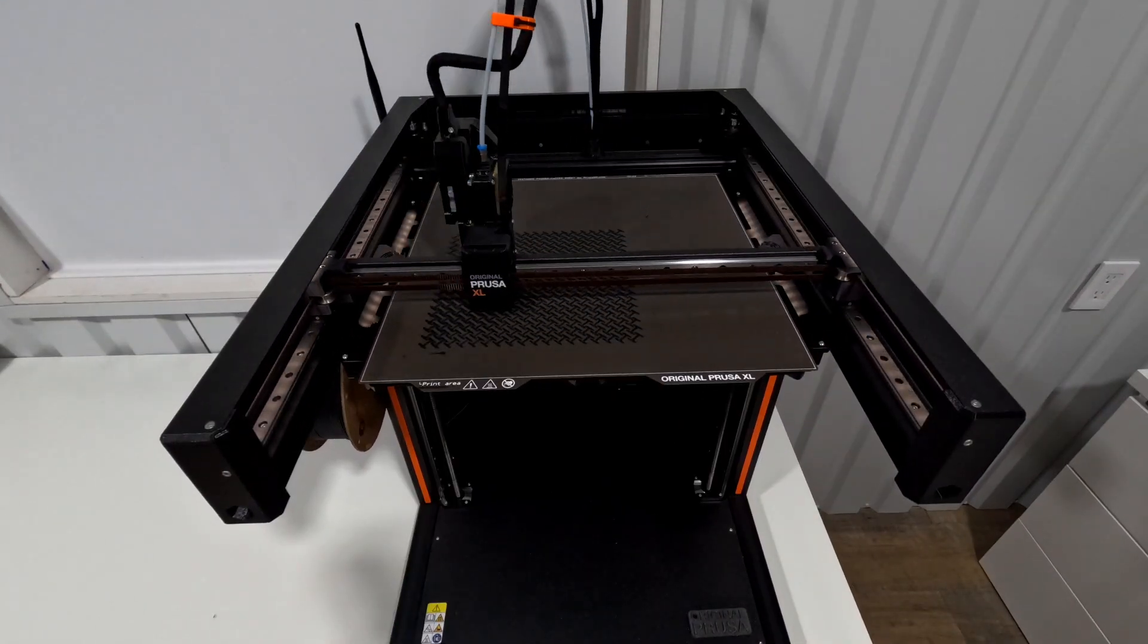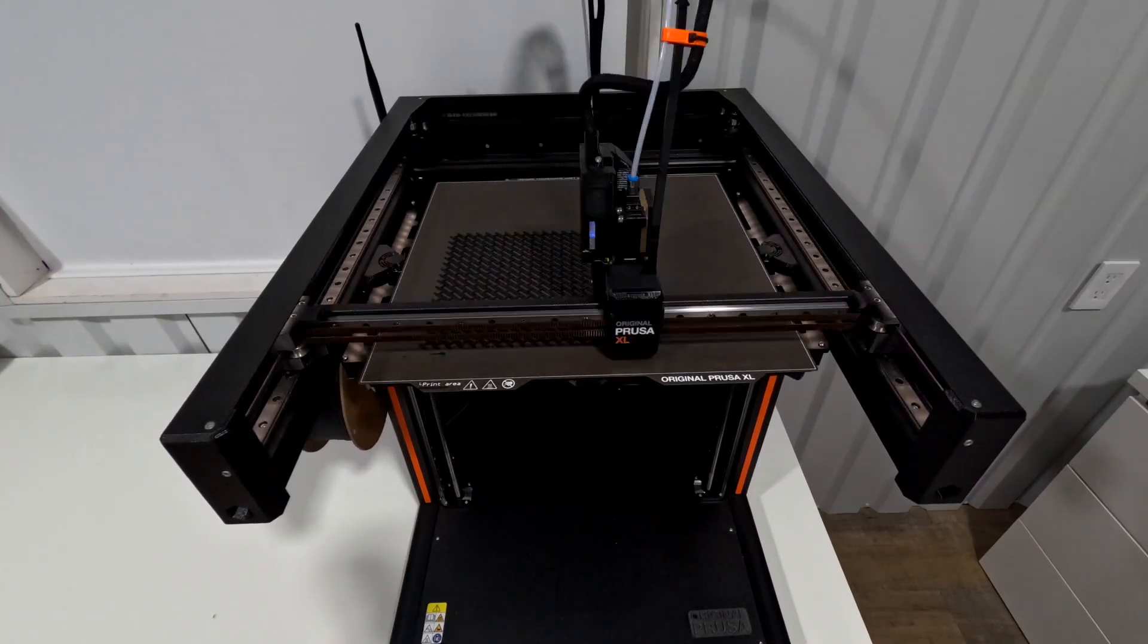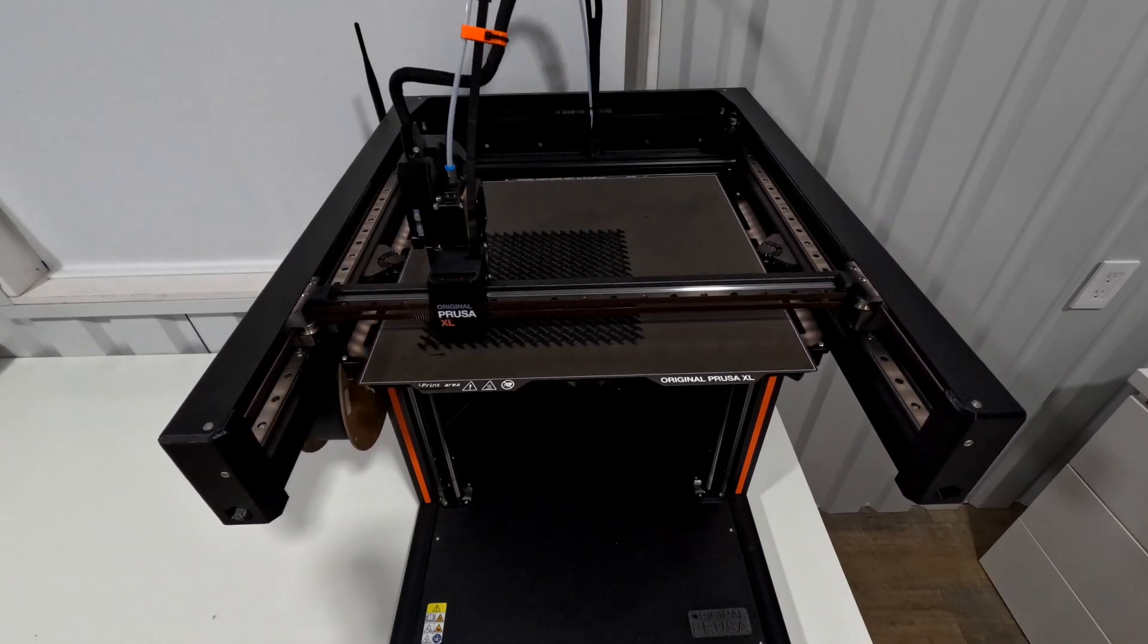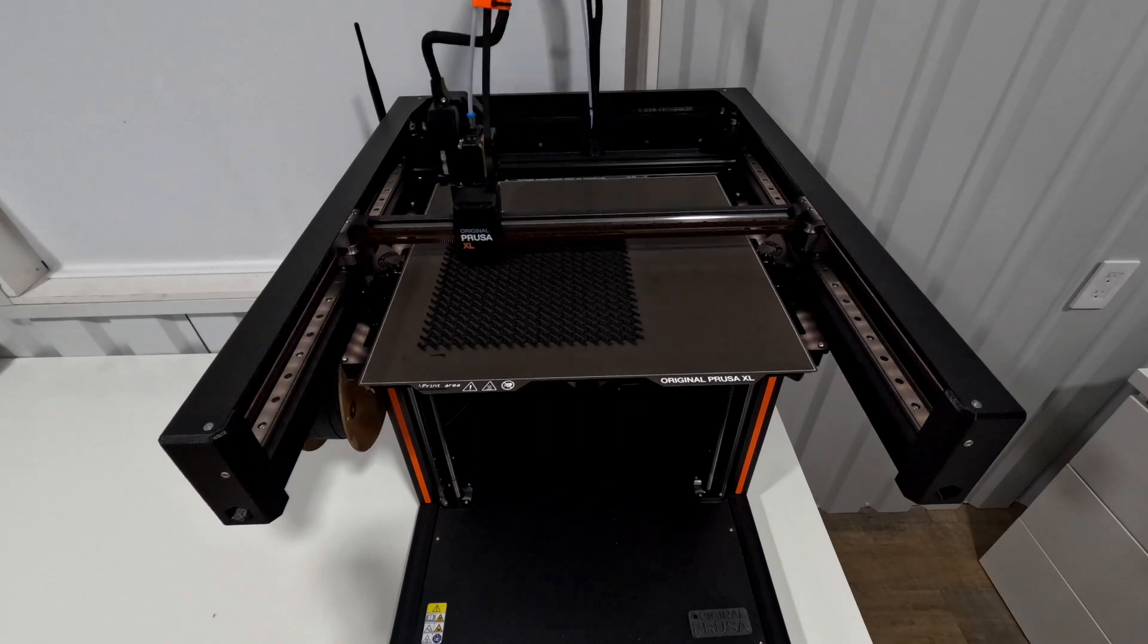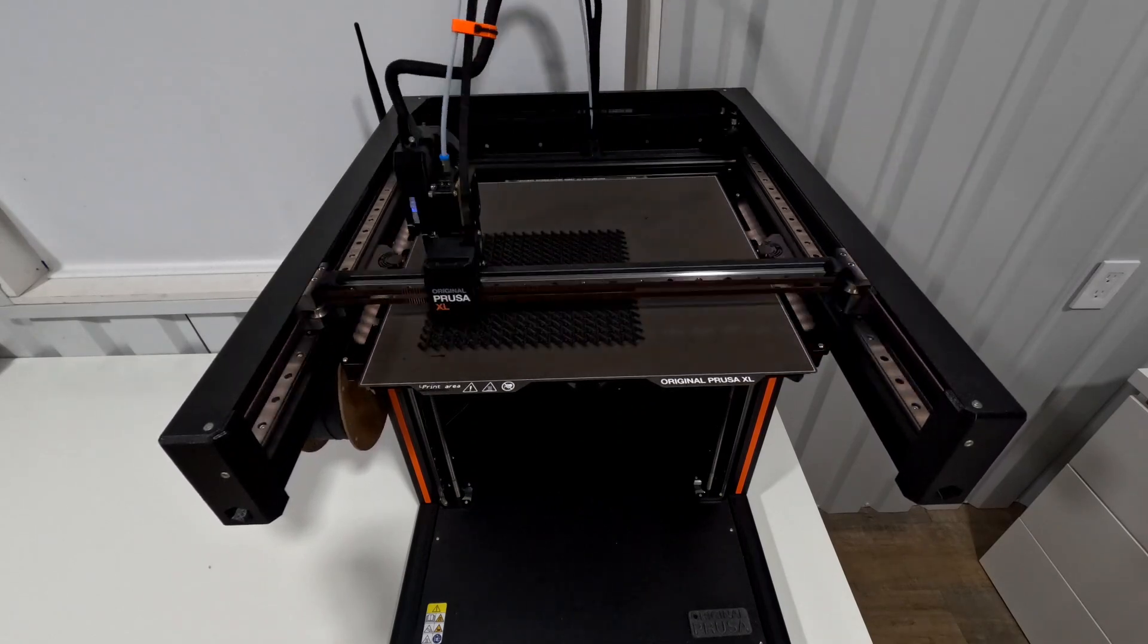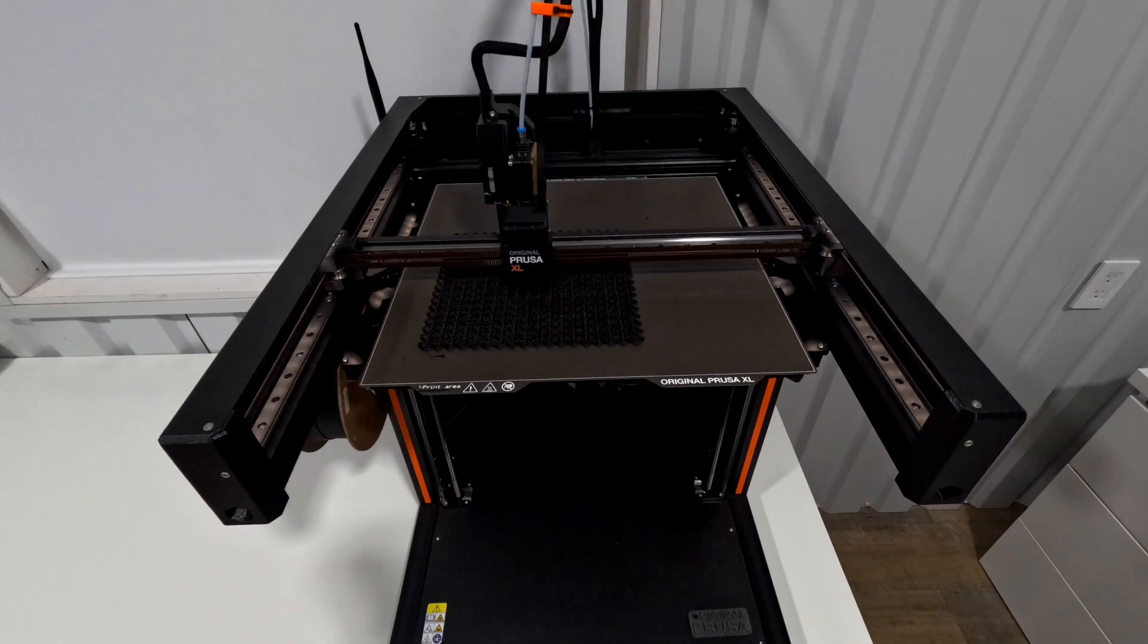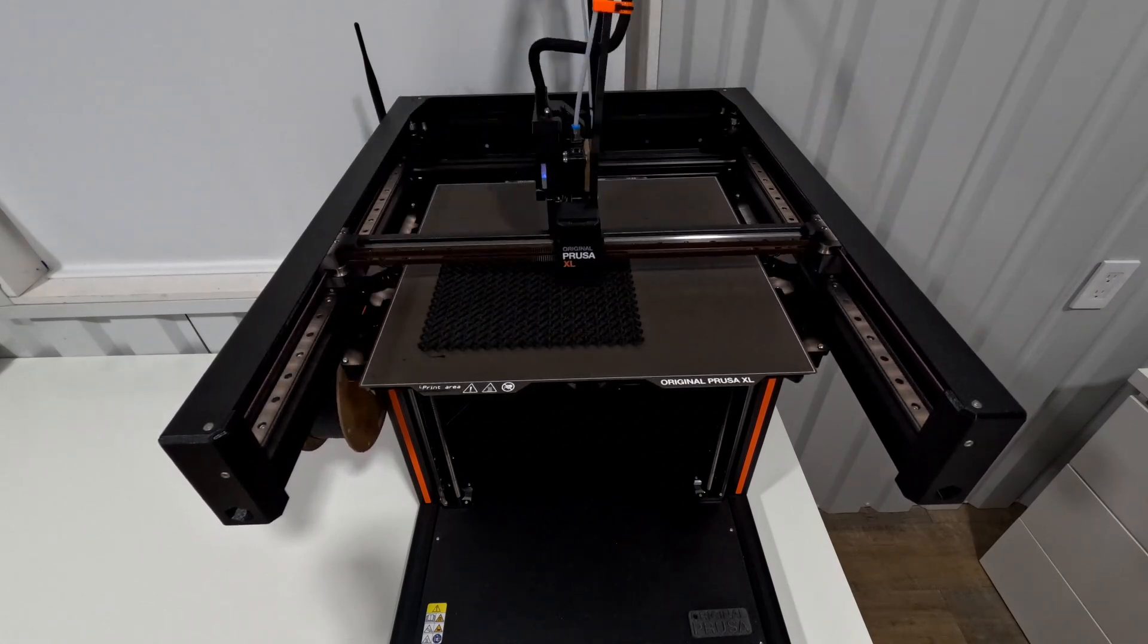My original plan was to go ahead and start it as the full 100% scale that it downloads as. It's about 7.5 inches by 7.5. The details recommended a 0.2 layer height. With the default profile that ends up being a little over 7 hours for this print. Bed temperature at 100 and nozzle at 285.